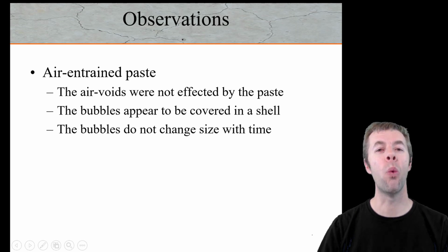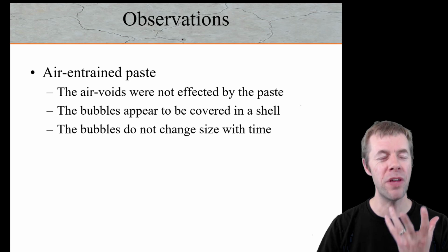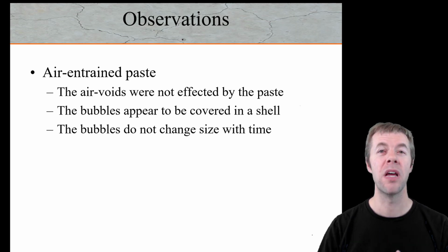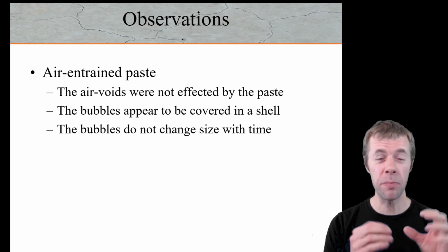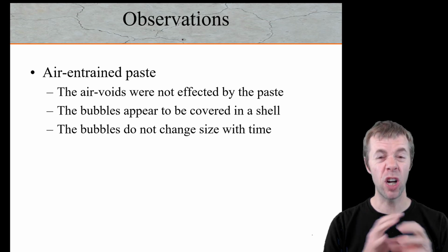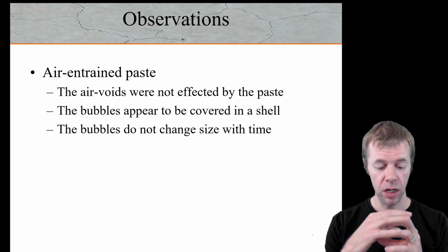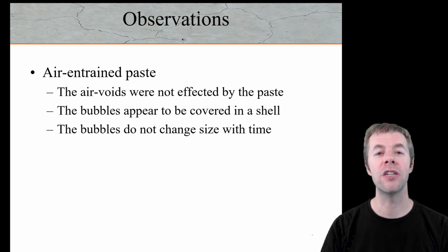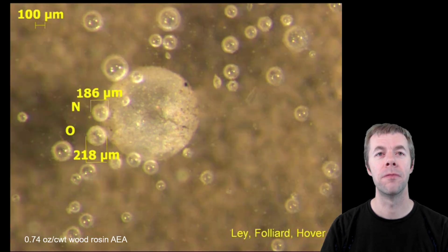That might be what you want if you're making concrete. You might want to make a bubble system and then have it stay there. So this was air-entrained paste, and the air voids were not affected by the paste. The paste didn't come up and crush them. The bubbles appear to be covered in a shell. Do you notice the difference? There's this shell around them. And the bubbles don't change size with time.